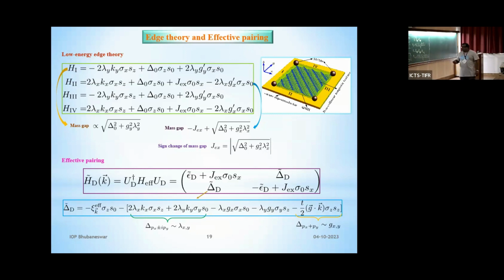And there is another way to see the effective pairing in this second order phase. If I do a dual transformation, by this unitary transformation, I can write a dual Hamiltonian. By doing this, I can predict that the effective pairing has two kinds. One kind of pairing is Px plus iPy, which is proportional to the intrinsic spin orbit coupling of the quantum spin Hall. On the other hand, you will have a delta Px plus Py type pairing, which is proportional to the pitch vector of the impurity. And these two types of bulk pairing are responsible for having this second order phase in the bulk.